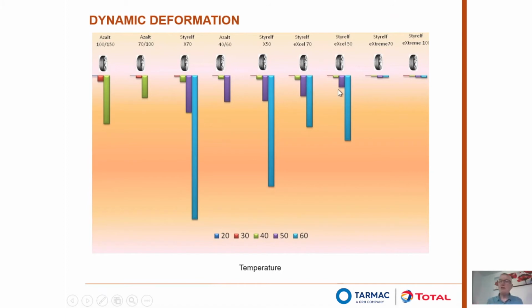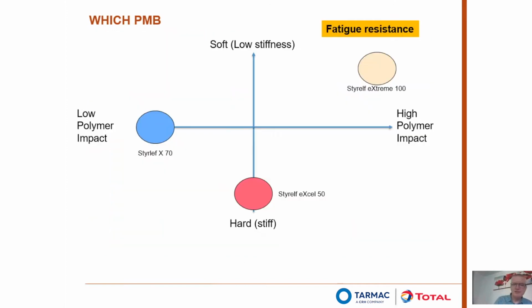But right at the extreme of the polymer impact, we have the Styrelf eXtreme 100. And you can see that even at 60 degrees C, even though it's a soft bitumen, the impact is fantastic because it's that elastic recovery which is stopping that permanent deformation from occurring. So even though it's contrary to what you might expect, because it's low stiffness, it's very polymeric and very elastic, and that helps resist that dynamic deformation.